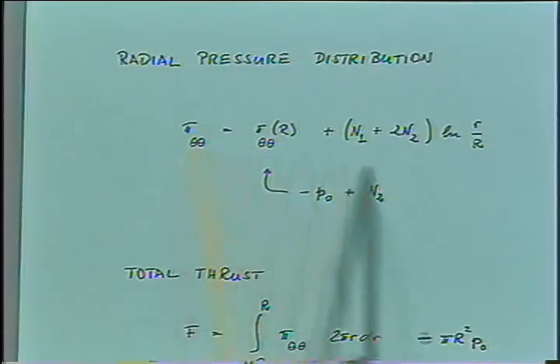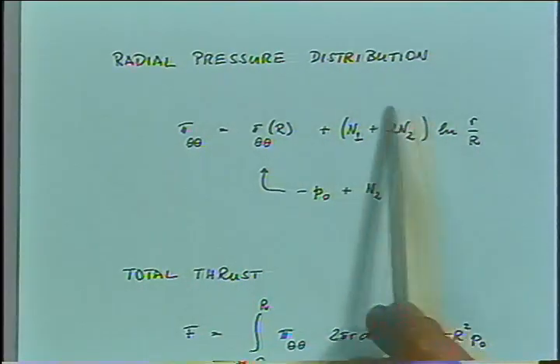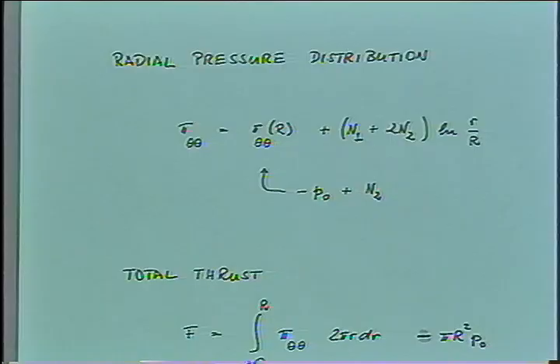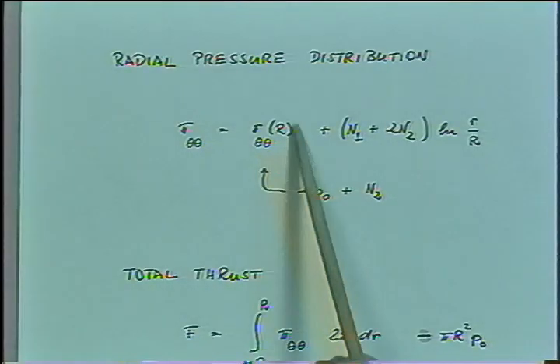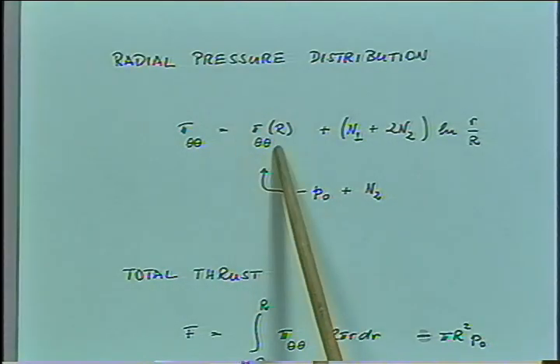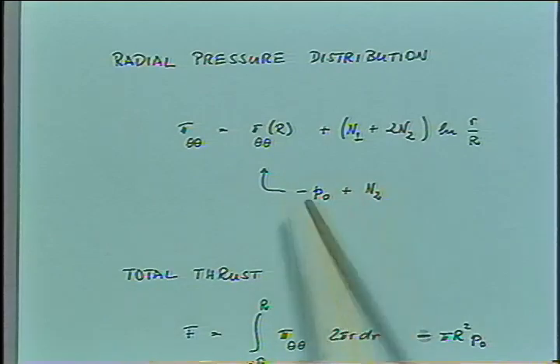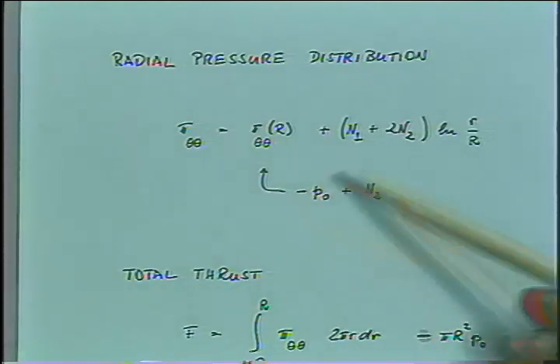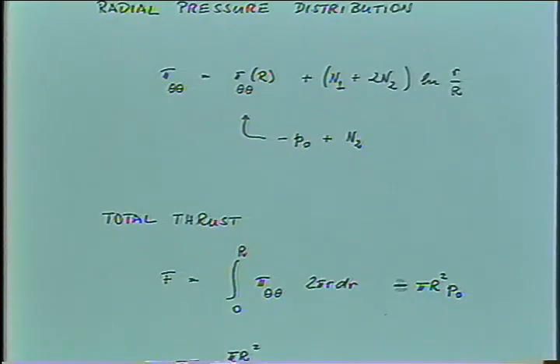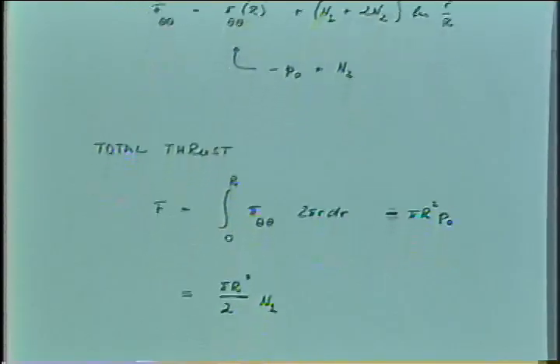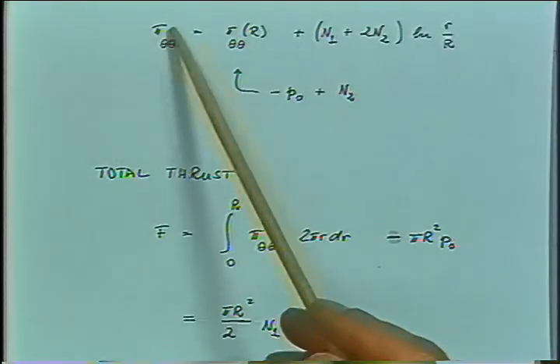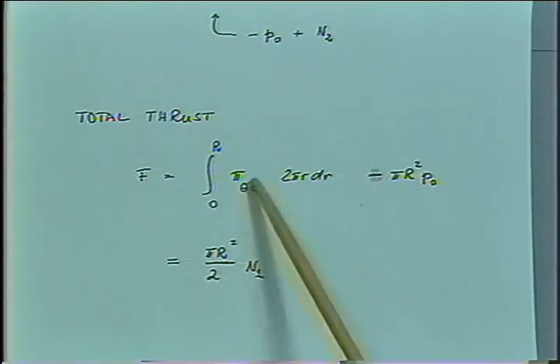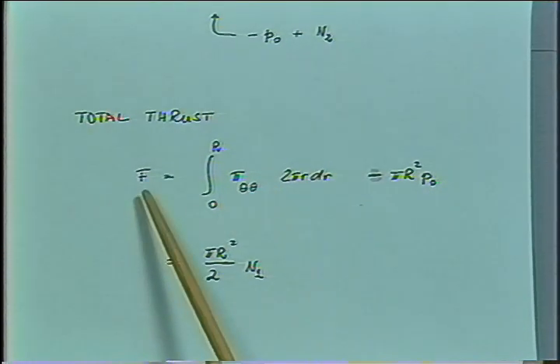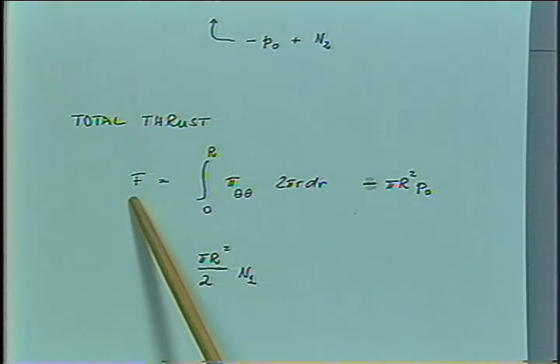This distribution is calculated as a function of shear rate coming in with N1 and N2. It also depends on the normal stress at the rim, which can be expressed with the normal stress sideways and the second normal stress difference. So that's all set, and you can integrate now. You can put the normal stress into this term here to calculate the total thrust on the plate or on the cone.